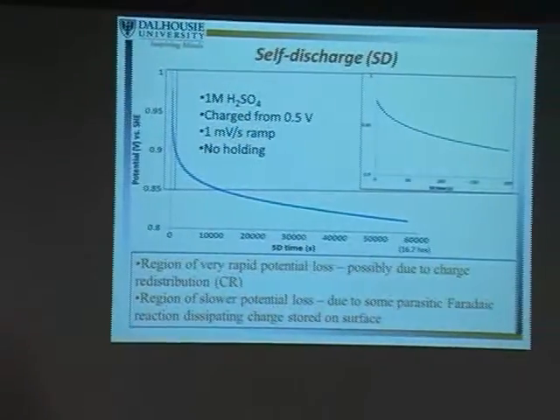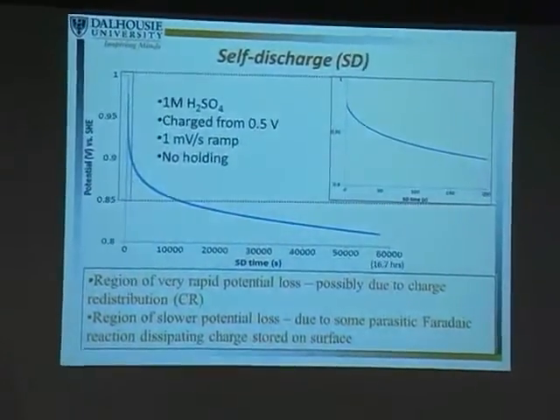And the issue is what we call self-discharge. So you charge up your supercapacitor, you leave it in a stored, charged state, and over time it loses potential. And we see that here. So this is a supercapacitor electrode. We've charged it to approximately 1 volt, and we see that it loses a significant amount of its potential in only 17 hours. And so this is a real problem.